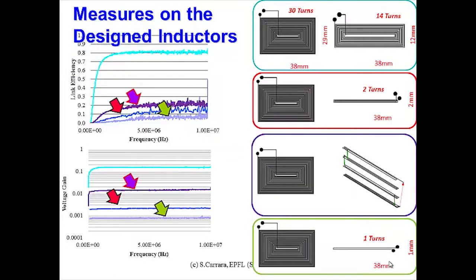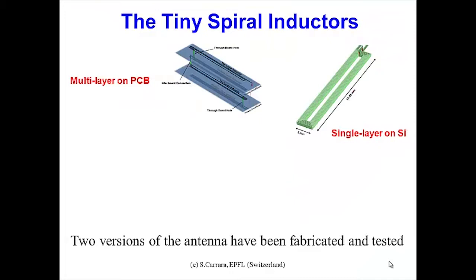So the solution was to try to develop the turns not laterally but in the Z direction, in order to keep the lateral size of the device very small. Actually, we tried two different technologies. One was to realize a multi-layer in copper, realizing a flexible PCB platform, and the second trial was to design metal antennas directly on silicon in order to have a deep integration with our silicon platform. In the second case, honestly speaking, we found a lot of problems to realize the multi-layer turns.